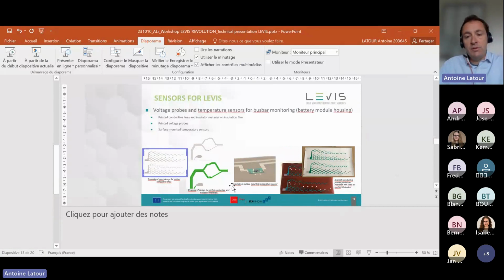So we have a contact between this probe and the metallic part to get a voltage measurement, but we are also able to mount temperature sensors at different localizations of a bus bar in order to get a rather good thermal mapping of the bus bar, to monitor heat propagation or strange behavior of the cells during the working of the cell.